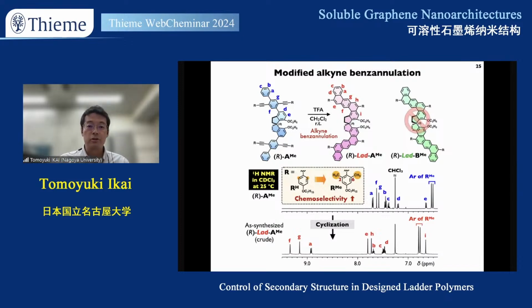To address this issue, we optimized the reaction condition and substrate structure. It took about 2 years, but we finally found that methyl groups introduced at the 2 and 6 positions of the alkoxyphenyl pendant significantly improved the selectivity of this reaction. And this perfectly suppressed the side reaction, probably due to the electron-donating ability and the steric effect of the methyl group.